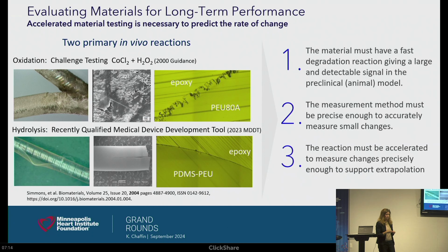When you put a material in the body, there's 2 main reactions, hydrolysis and oxidation, right? I showed you some of that oxidation. You get these rough surfaces, you get opacity. A lot of people, to measure oxidation, have just looked at surface roughness with optical microscopy or scanning electron microscopy. But we now know that that doesn't tell you about oxidation because there's some parts of that fibrotic capsule that maybe don't give you that surface roughness. But that's where the industry is. You can look back at these references here.